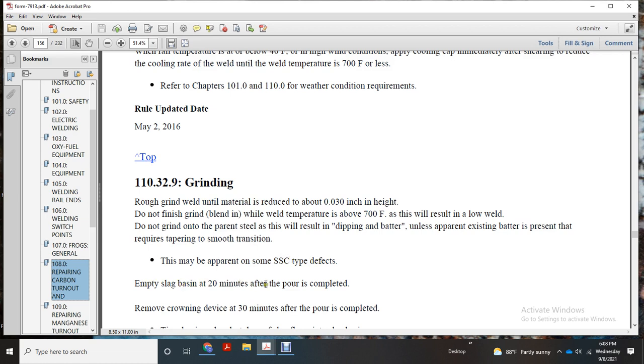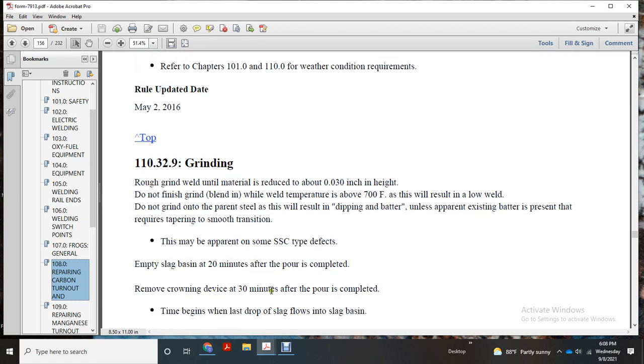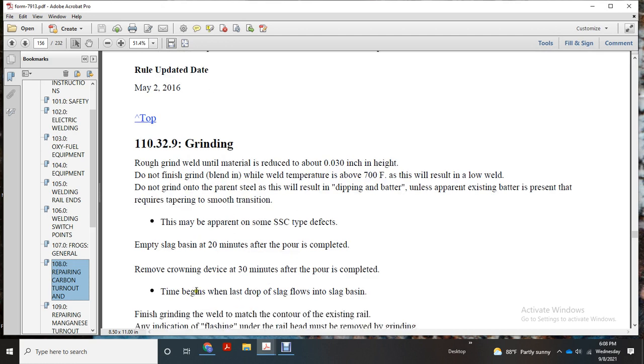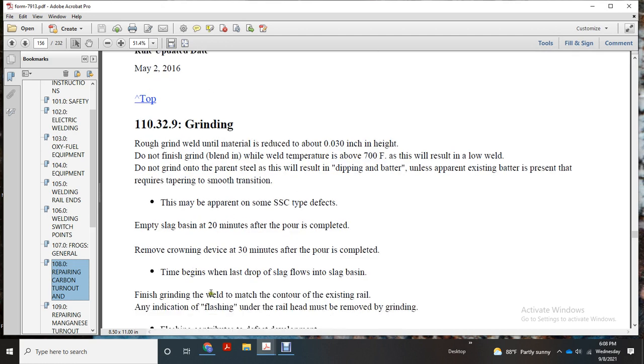Empty the slag basin 20 minutes after the pour is completed. Remove the crown device 30 minutes after the pour is completed. Time begins at the last drop of slag flowing into the slag basin.